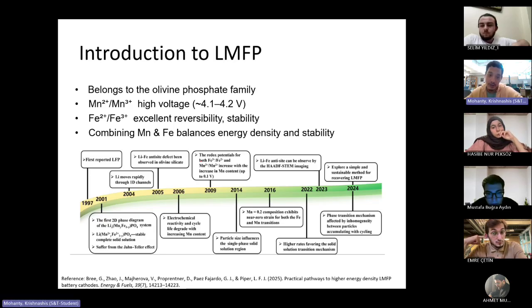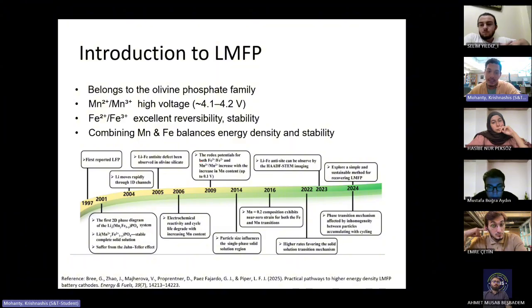Maybe the difference of the redox reaction, if higher, could lead into complications and could lead to a wider Fermi band, which makes it hard for electrons to travel into the conduction band. So this reaction, even though it has higher energy on paper, it is quite achievable. So that's why we pick manganese of all elements, because it's convenient.